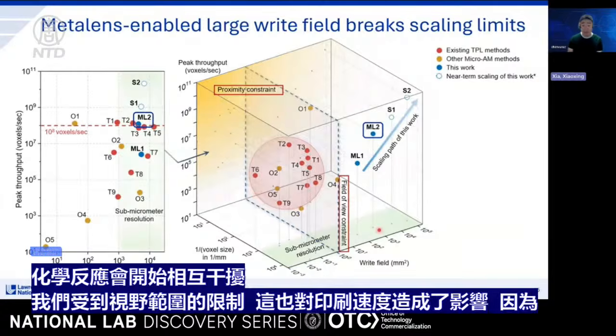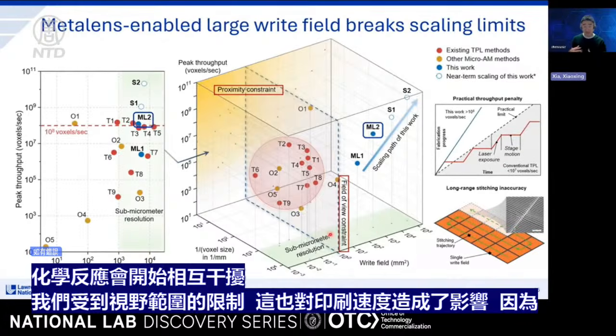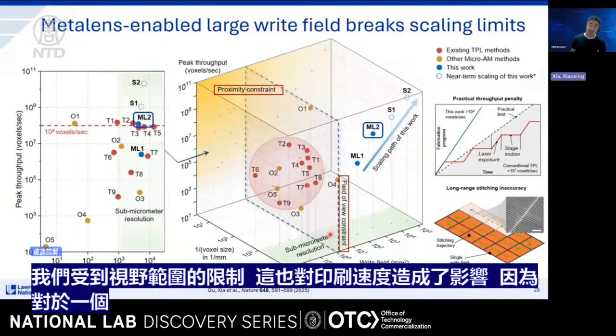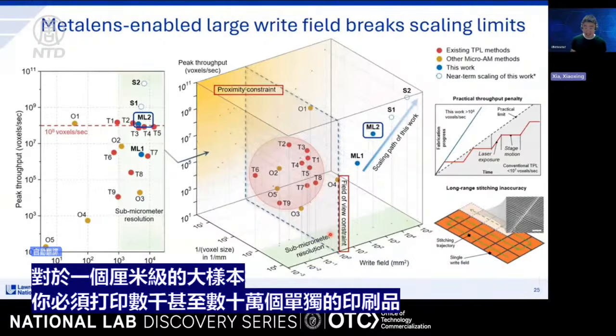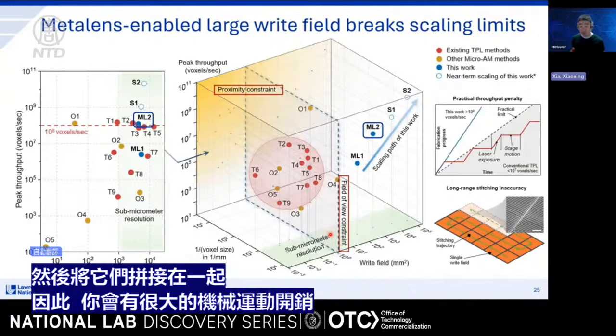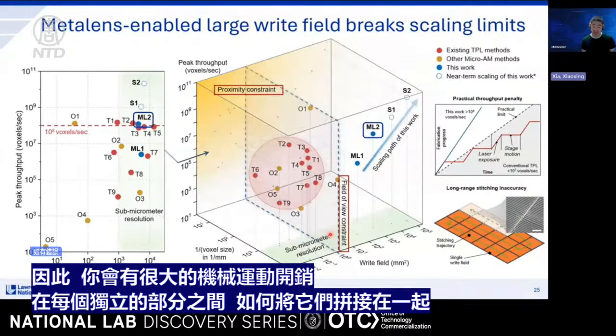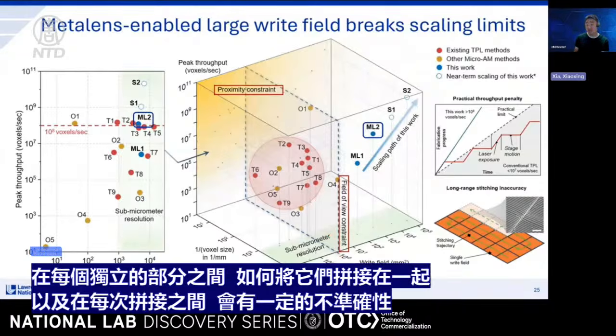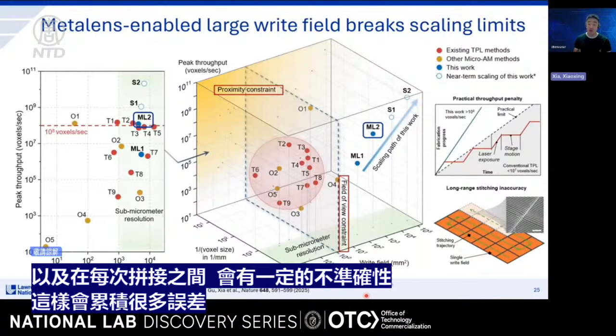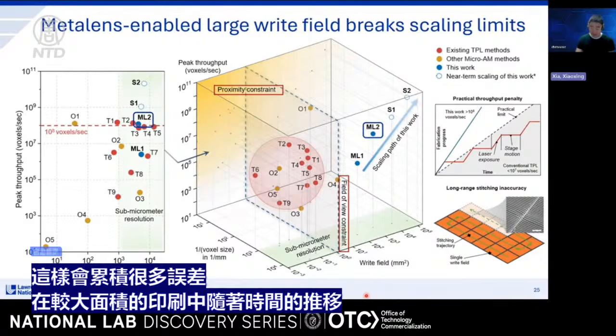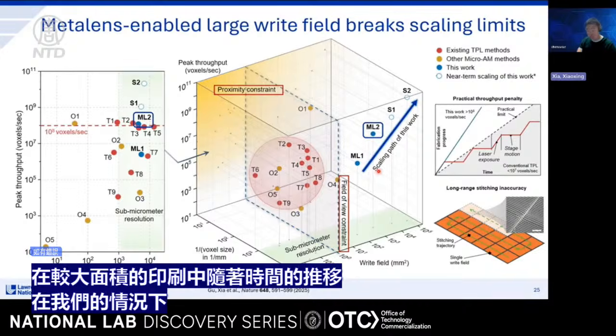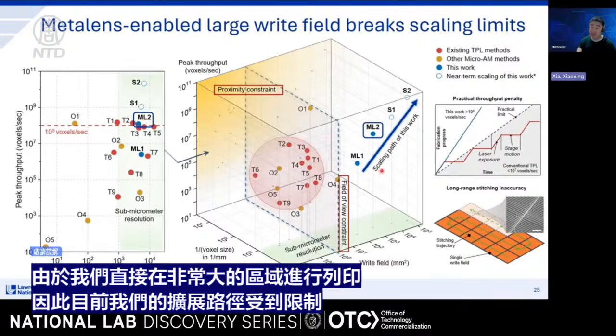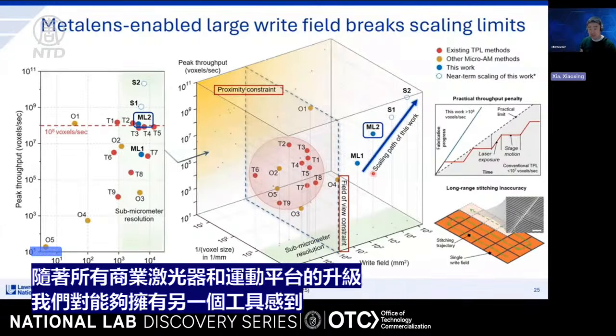And the fact that we're bounded by the field of view also takes a toll in terms of printing speed, because for a centimeter-scale, larger sample, you have to print hundreds of thousands of individual prints and stitch them together. So you have a very large overhead of mechanical motion between individual subprints, and how do you stitch them together, and also between each stitching there's a certain inaccuracy, and you accumulate a lot of error over time on a larger area print. In our case, because we're printing at a very large area directly, our scaling path is unhindered at the moment. With off-the-shelf commercial upgrades of lasers or motion stages, we are quite confident that we can have another 2 orders of magnitude enhancement in printing speed.